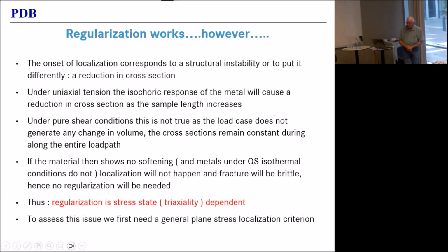So regularization works. At least in uniaxial tension, it works. Well, it works because in uniaxial tension, there is no doubt that we have necking, that we have localization. That will be the case for the vast majority of metals, with the exception maybe of a few castings. But it's not always the case.